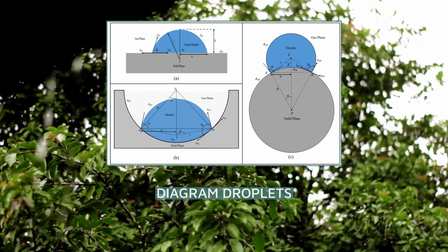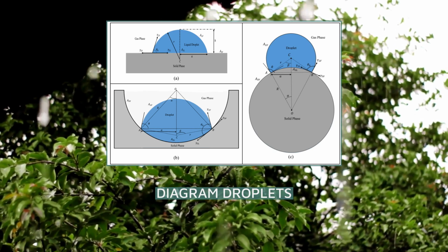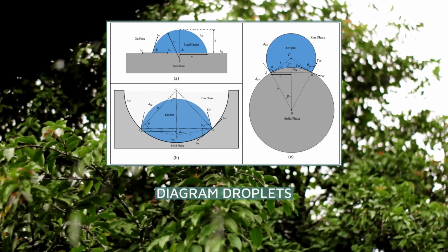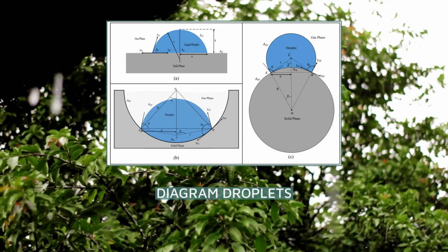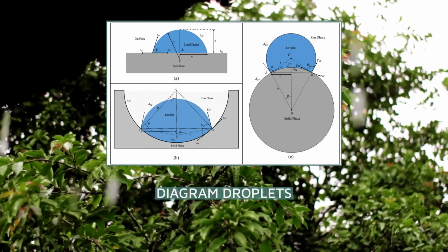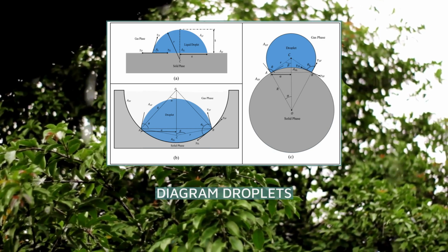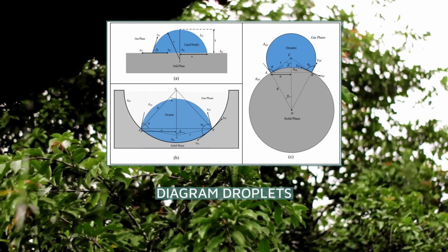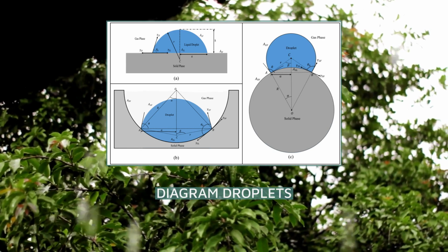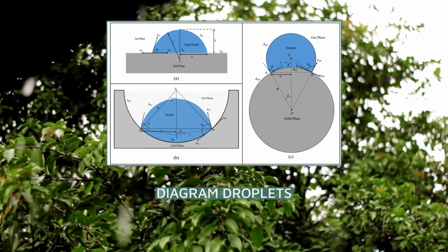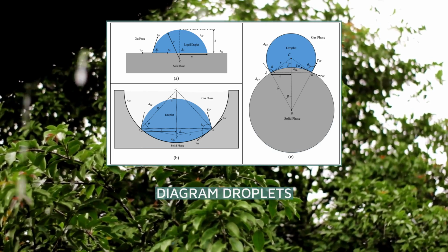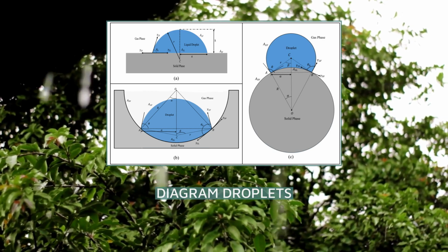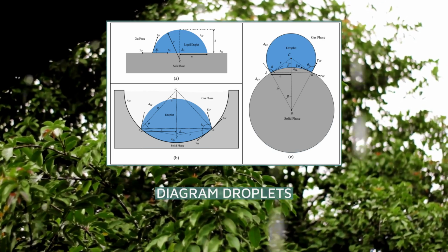For the special case of a sessile droplet on a flat surface, α equals 0, and the equation gives cos θ as the sum of the Young term, a line tension term involving κ, and a third term from the Laplace pressure. The first two terms are the modified Young's equation, while the third term is due to the Laplace pressure. This nonlinear equation correctly predicts the sign and magnitude of κ, the flattening of the contact angle at very small scales, and contact angle hysteresis.